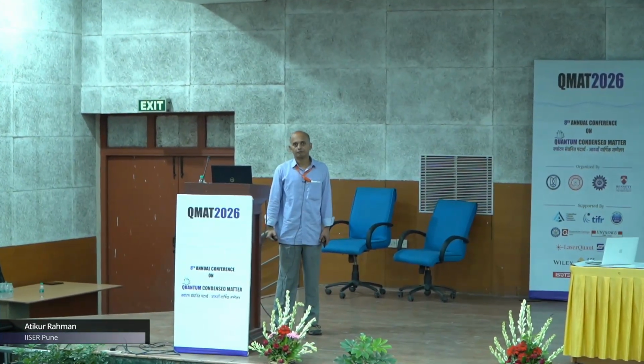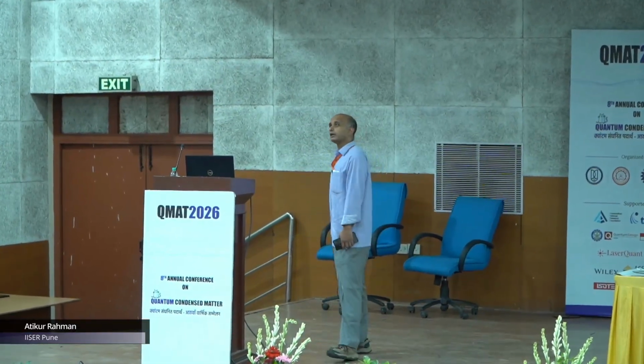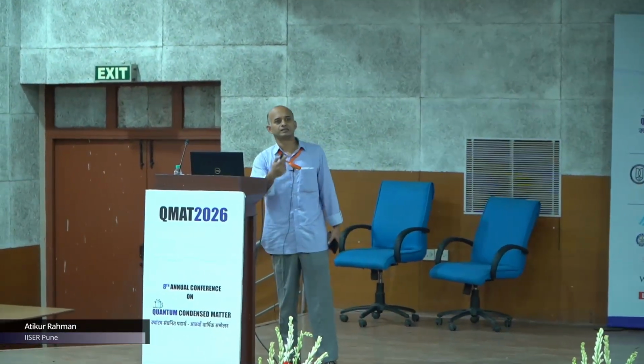So are you planning to engineer anything to increase the fill factor? Instead of trying to increase the fill factor, we are trying to improve the current, because there is some fundamental limitation on increasing the fill factor. We can try to increase the current, because the voltage we are already getting is pretty high. People even got up to 30 volts in some ferroelectric material. So you are trying to combine this with a ferroelectric layer and see if it improves at least the current to a certain extent.